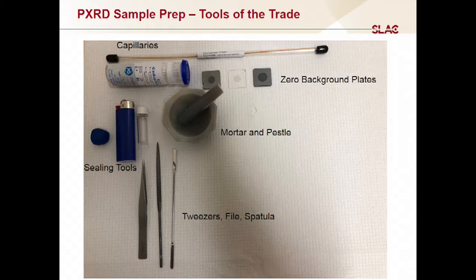If it's something very heavy, like a silver complex or a gold complex or something of that nature, it can be quite thin, and the X-rays won't penetrate very deeply, and so then you can get away with less material because you don't need quite as much thickness to the sample. The other thing that you want to think about is if you have a flat plate sample, it should be flat.